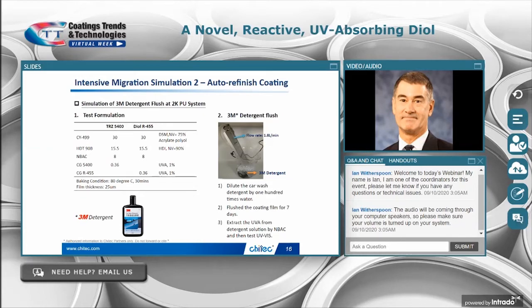Okay, in this next test, we're using 3M car wash shampoo to see if a simple water soap solution can impact migration loss of free UVA from cured films. We used a 2K polyurethane formulation for this test. The soap solution was pumped across the surface of the coating without agitation. You can see the setup is here. We are trying to simulate a realistic, longer-term, many car wash type situation.